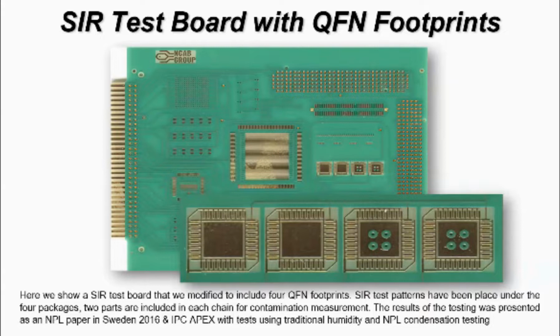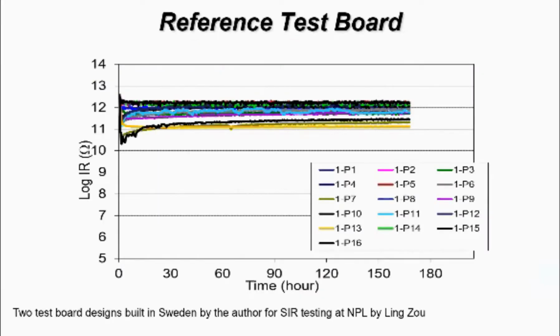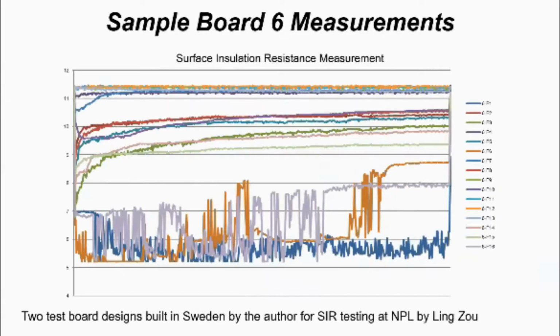And there's a lot more information I can give you on this, but this is just simply giving you a view. And we put this through the process of SIR testing that most of you will be familiar with. And this is just a reference sample board, which is part of the testing that Ling Zou does for many customers at NPL. And you can see what I refer to as the squiggly lines, or the resistance values. And here's an example of a failed sample. And you can see 3 or 4 points of interest well below the level that would be considered unacceptable for SIR.